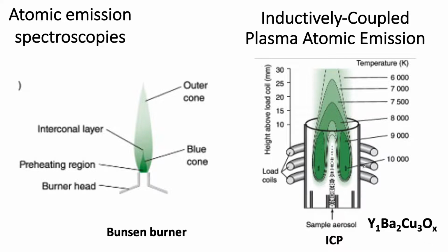And so I would see emission lines, and then of course I had to calibrate this. To do that, you would buy from a vendor a bottle of something that they would tell you was, say, 1 part per 1,000 or something like that of yttrium in water, yttrium oxide dissolved in water, or barium in water. So I had 3 different calibration sources, and I would dilute those down so that they were similar to what I was going to be measuring, and then I would do a separate calibration run to see how it responds with known concentrations of yttrium, barium, or copper in the water.